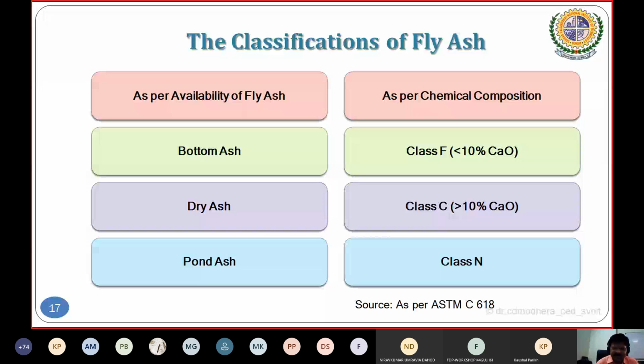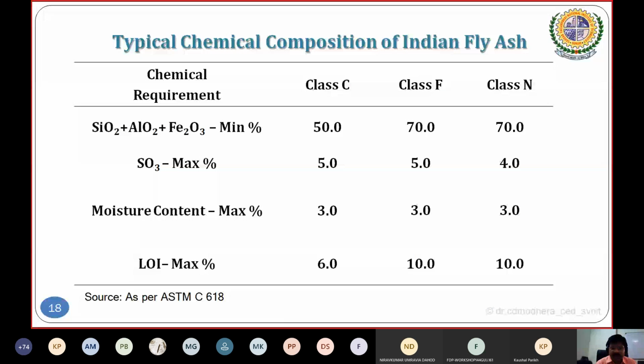Typical chemical composition of the Indian fly ash I have kept over here: class C, class F, class N. And then you can see the LOI is not more than 10%. And you can say moisture content also is more or less uniform. But a little variation is seen in class C between F and N. And SO3 is more or less similar. Class C is again discussed in detail.